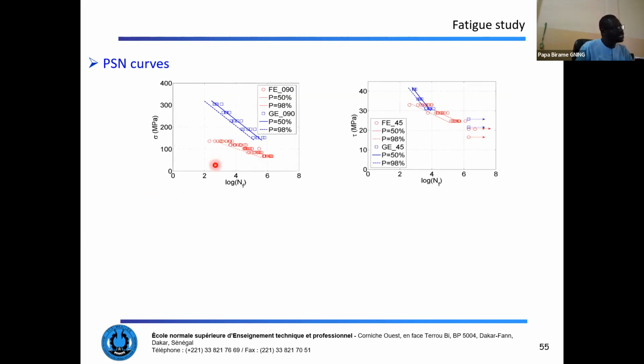So the tensile loading results can be compared to glass ones, which are plotted in blue, knowing that the flax are lower here in red. So we see that the long-term behavior of flax is quite lower than that of glass when we approach the millions of cycles.